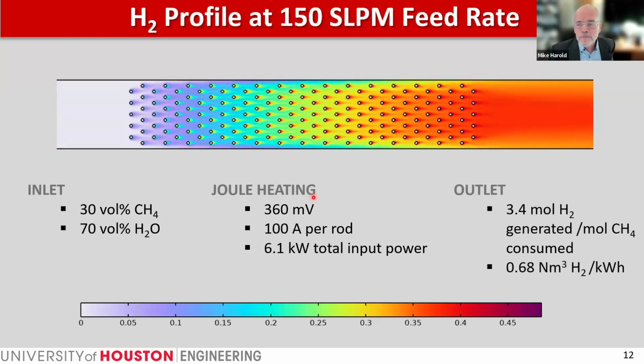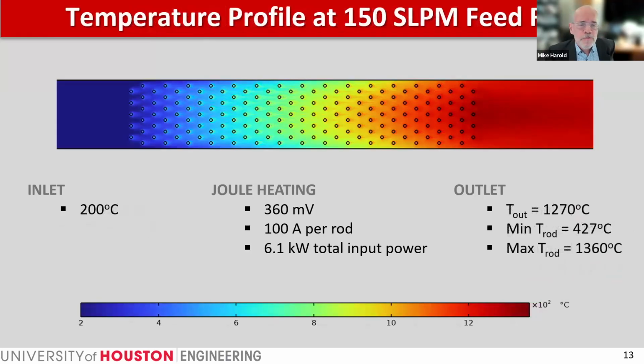The corresponding hydrogen profile is here. We can quantify the amount of hydrogen generated per mole of methane consumed. It's about 3.4 moles, so somewhat over 3, with the forward water gas shift participating in the generation of additional hydrogen beyond the 3 for SMR. We can also calculate a hydrogen production per power kilowatt hour of nominally 0.68 normal cubic meters of hydrogen per kilowatt hour. Here's a temperature profile.